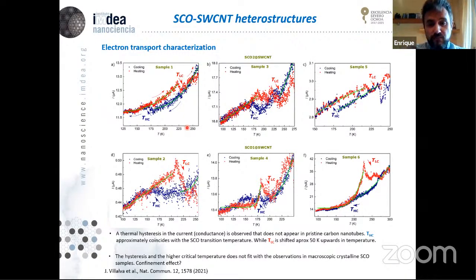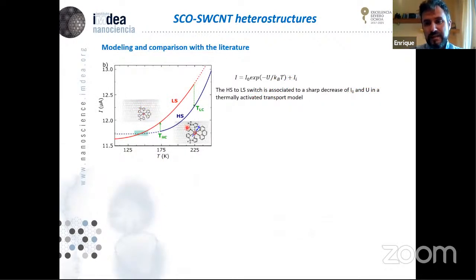So what this looks like is happening here is that the current in the carbon nanotube is sensitive to the spin crossover transition. That's why we are here in this high spin state. When it switches to the low spin state, we have a switch to a different state. But what is very strange for us is that we have this thermal hysteresis. The crystals of the molecules do not have thermal hysteresis, okay?